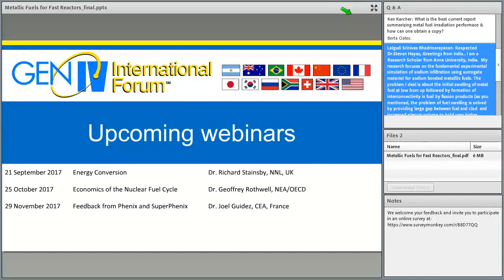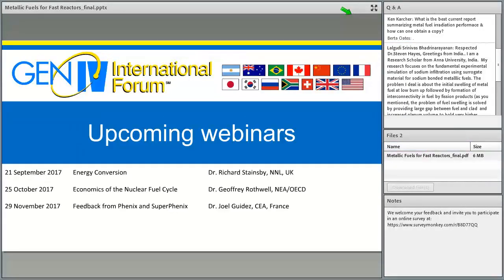And there's a very long question. Looking at a very long question here from India, talking about experimental simulation of sodium infiltration using surrogate materials. We've been looking at a little of that too, probably not as much as you. It says the problem I deal with is the initial swelling of metallic fuel at low burnup, followed by interconnection. Yes, the problem of fuel swelling is solved by providing a large gap between fuel and cladding. Yes, that's all true. Liquid sodium in the fuel infiltrates into the fuel and does, I agree, lead to some recovery of fuel thermal conductivity, which is degraded by the swelling. And it says, please let me know about numerical validation for variation in thermal conductivity before and after sodium infiltration.